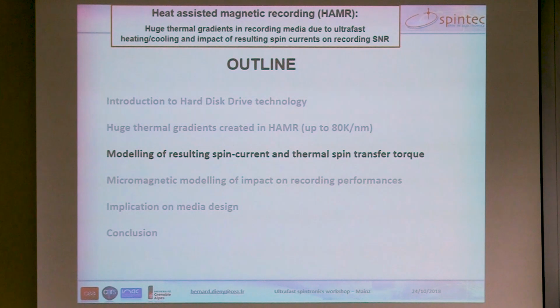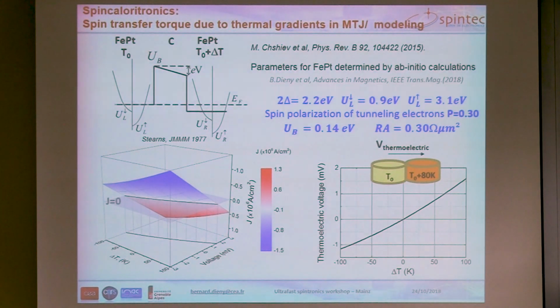So let me now move to the modelization of this effect. And actually, we use the same formalism as with magnetic tunnel junction. So we consider here a tunnel barrier separating two magnetic electrodes. And in this magnetic electrode, we describe with this well-known band-splitted model of itinerant electron, which was first proposed by Maribeth Stearns in 1977. So actually, the formalism that we used is described in this paper here.